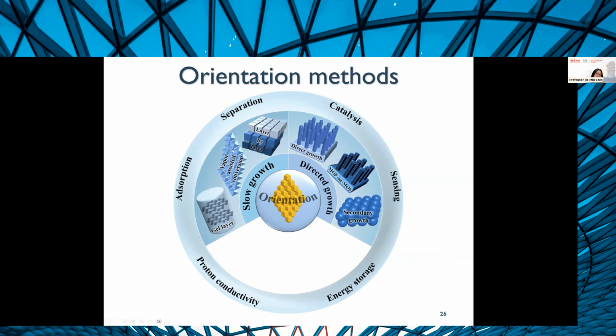There's been work to try to control MOF orientation. A lot of work has been done to control the growth of MOFs via gel layers or layer-by-layer growth or pseudomorphic conversion. But typically, this is very slow. It requires very precise control. But it does give you beautifully oriented MOF materials. You can also have directed growth on different substrates, like what I showed you, where you had MIL-53 growing on an aluminum oxide membrane. In this case, you also need to consider the compatibility of the substrate with the MOF you're using. And you really need to consider the growth conditions.